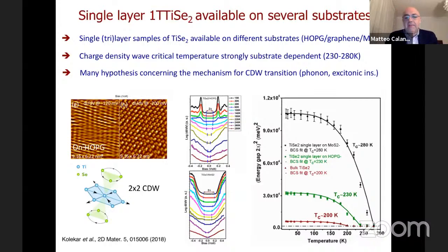to minimize the Coulomb repulsion. So on the contrary, in the high temperature phase, all these titanium stay exactly on the hexagon, and the selenium are at the position where you see the green balls. And so. Now, if you put them on different substrates,